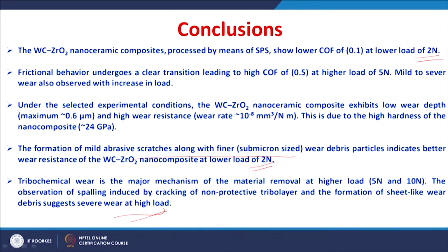So, this particular study indicates that the wear behavior of this tungsten carbide zirconia nanoceramic composite depends on the load as well as the fretting duration. The mechanism of material removal changes from mild abrasion to tribochemical wear with the change in the load from 2 Newton to 10 Newton.